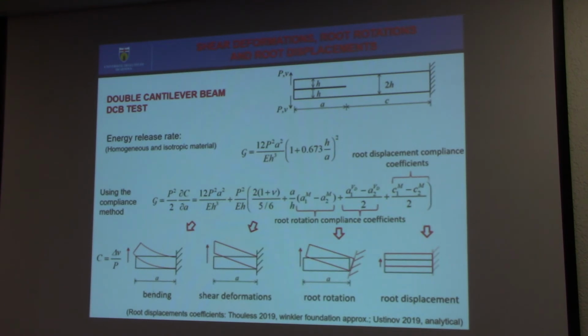We can also use a different approach to calculate the energy release rate. We can use the compliance method, and the compliance is the transverse displacement here due to a unit load. If you apply the compliance method to define G, then we can separate again all the different contributions, and we will see the effect also of the root displacement, which needs to be taken into account in the solution.